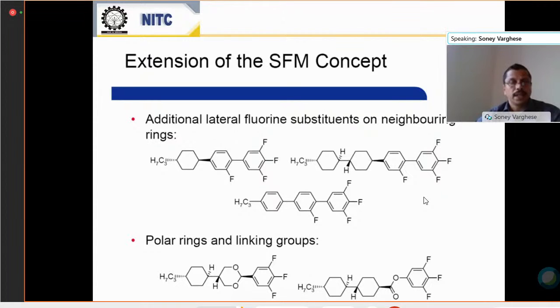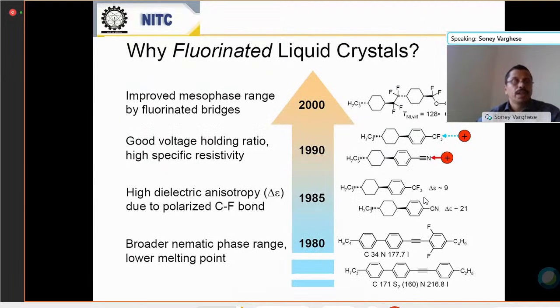So basically, the function of fluorine is to introduce the polarization, right? Because polarization is very important. And you can see that why we are going behind fluorinated compounds is to improve the mesophase range, right? And also good voltage holding ratio and good specific resistivity, high dielectric anisotropy.